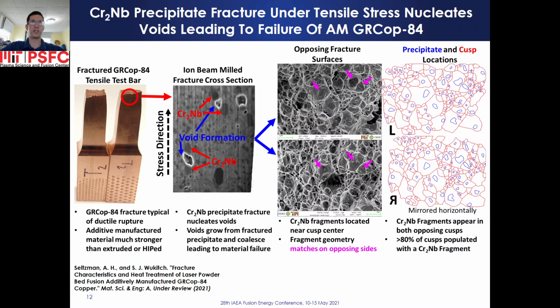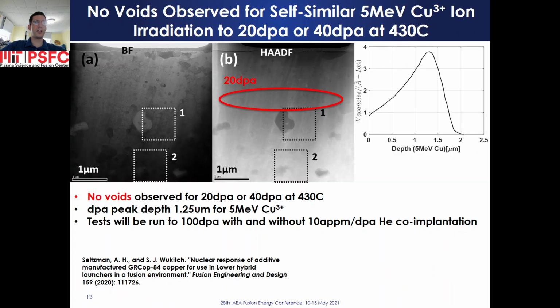void nucleation. Promising nuclear characteristics of GRCop-84 are examined with self-similar ion irradiation with 5 MeV copper ions. No voids were observed in TEM studies after either 20 or 40 dpa irradiation at 430 Celsius. Low boron content, as well as grain and precipitate size similar to copper alloys resistant to swelling under neutron irradiation, predict promising behavior in a fusion environment. Future ion irradiation to 100 dpa with 10 appm per dpa of helium co-implantation will further examine the potential reactor